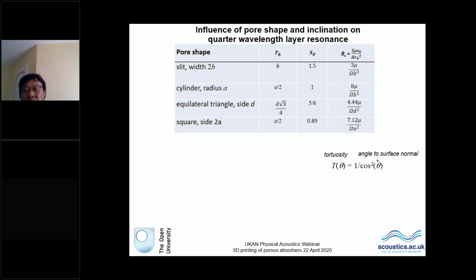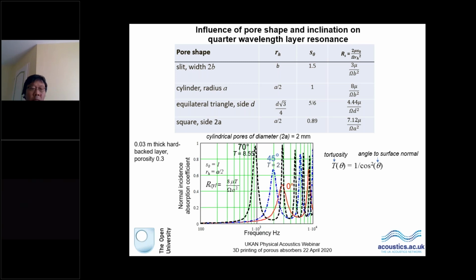Something that's been known since, I think, 1949 or perhaps earlier, the time of Zwicker and Kosten, is if you angle the pores, incline the pores with respect to the surface, then you increase the tortuosity. And what I'm talking about really are going to be all the microstructures that can help increase the tortuosity, because if you're looking at a thin layer of material, that's a very important parameter to try and increase in terms of shifting the first layer resonance to a lower frequency. By the way, that also relates to slowing the sound speed within the material in a different way to the way that Philippe discussed. So you can see immediately for these particular set of parameters how going from normal to the surface to 45 degrees to the surface to 70 degrees to the surface, you shift that low frequency peak absorption.